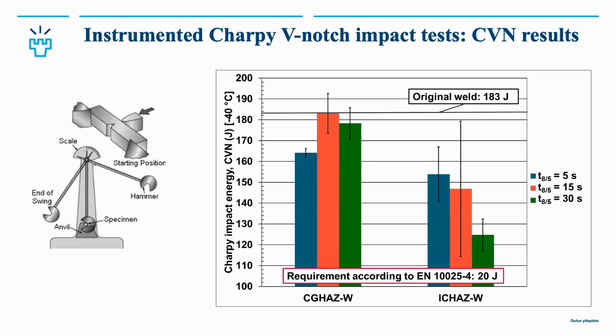Then about the impact toughness results. So the original weld impact toughness is here, and you can see that in the coarse-grained heat affected zone there is not much variation. It is a bit less, and with the shortest cooling time there is a lower impact toughness than with the longer cooling time. But the lowest impact toughness was seen in the intercritical heat affected zone, and the trend was that it went down when the cooling time was increased. But still, even in this case, the lowest impact toughness easily exceeds the requirement according to the standard, which is 20 joules at minus 40 degrees. And here we are at more than 100. So still relatively good impact toughness anyway.